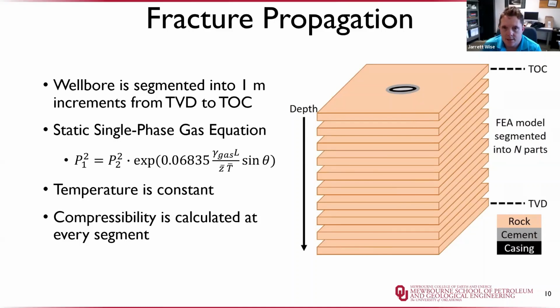We used this static single-phase gas equation shown on the screen to model the gas pressure within the microannuli to represent our fracture pressure. So this equation relates the inlet and outlet pressure with a specific gravity of the gas, the length of the segment, which was 1 meter in these simulations, I believe, the compressibility of the gas, and the temperature. For this model, temperature was assumed to remain constant, and the compressibility of the gas was calculated using the empirical formula from Shell for methane.